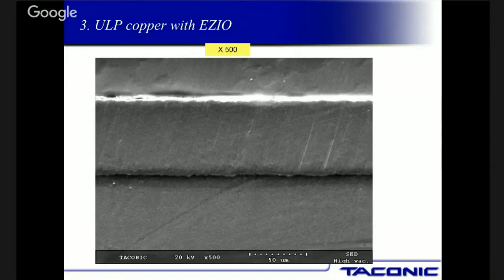And so what people are finding is that some of these platings are not good. They're whiskering, they're oxidizing, and there's just the higher temperature. You're taking a board which we used to process at 220 degrees centigrade, and you're now taking it up to 280 or 290. And there's a lot that happens in the board when you look at all the different materials, the prepregs or the different layers. That's what causes boards to warp. One layer is expanding this much, the next layer is expanding this much, and eventually you get it out of the IR reflow, and the board looks like a Lay's potato chip. And so that's what I say. All the companies are really sifting through what's the best process, what's the best treatment, what's the best board shop to build the board to meet their requirements. And every company, like Northrop Grumman, has completely different requirements than General Dynamics does.